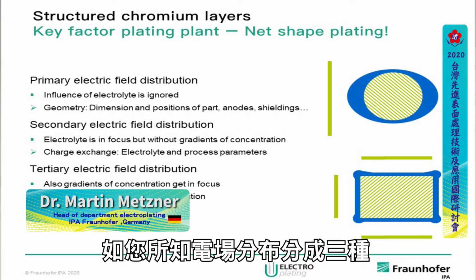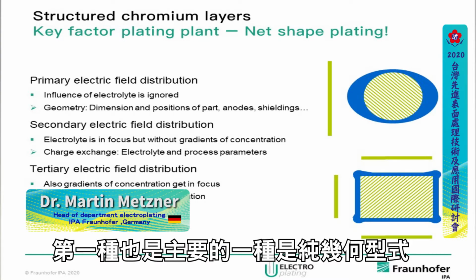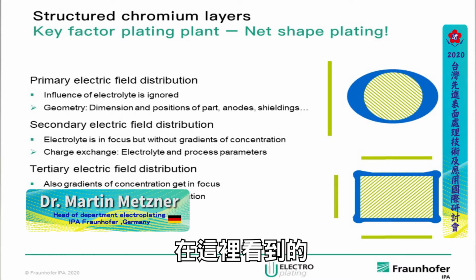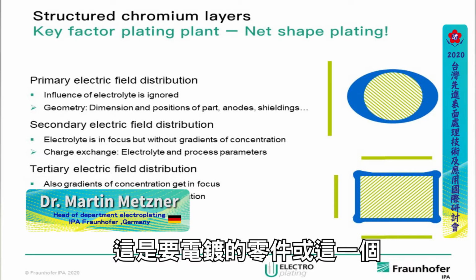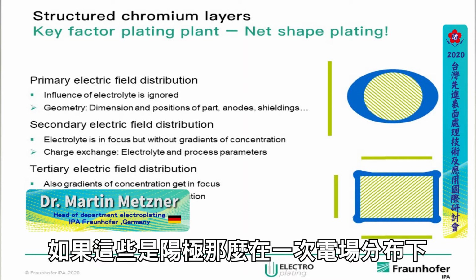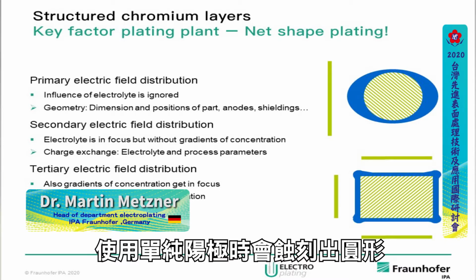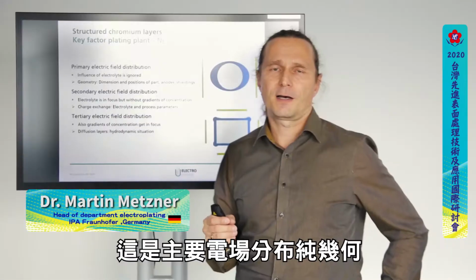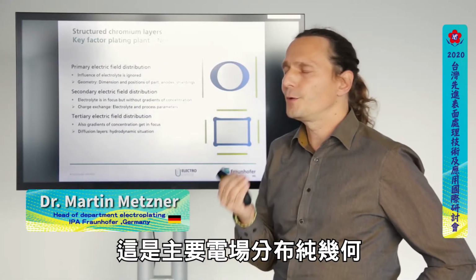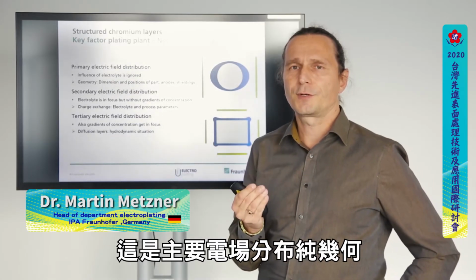As you know, we've got three different, what we call electric field distributions. We've got the first one, the primary one, which is pure geometry, what you see here. So this is the part to be plated, or this one. And when these are the anodes, then you know just from the primary electric field distribution, when we use plain anodes, we make an egg out of a round shape part. This is the primary field distribution, pure geometry.